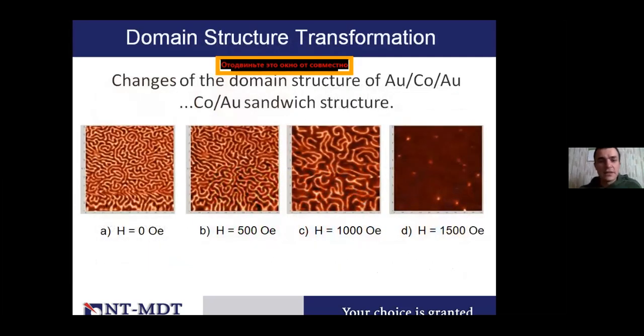And here is an example which shows you the change of the structure under different external magnetic fields. We increased the magnetic field from 0 to 1500 Oersted, and you can see how the structure is changing. And the sample is some domain structure, a sandwich structure. So it's gold together with cobalt.